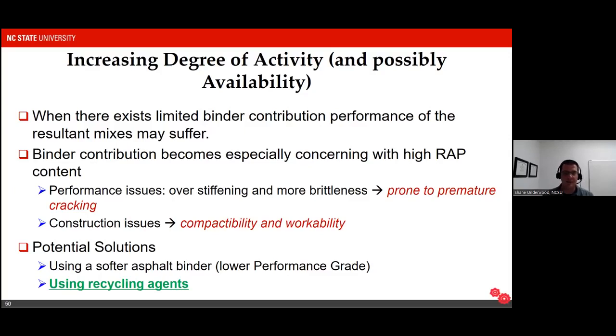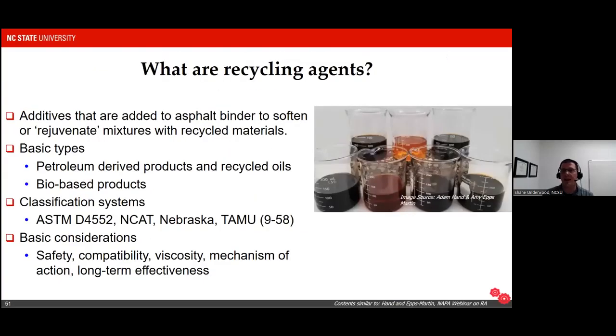Now, one strategy that has been becoming increasingly popular in the US is to use recycling agents. Now, recycling agents are an old material. They've been used in the US for many, many years, sometimes sold under different names, but the basic purpose of a recycling agent is to try and rejuvenate the mixtures and make the binders look like they originally did when they went into the mixture. So we're trying to reclaim or rejuvenate those asphalt binders. Sometimes these materials act more like softening agents, which is not what we want. Sometimes they act like extender oils, again, not what we want.